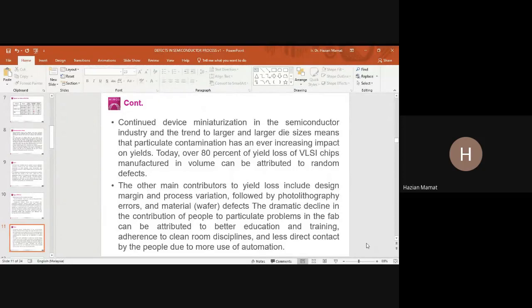Okay. But as we know, if we have a larger wafer size, we can keep the number of malfunctioning chips or defects to the lowest. That's why foundries are getting bigger and bigger wafer sizes. The other main contributors to yield loss include the design margin, process variation, followed by photolithography errors and material (wafer) defects. The dramatic decline in the contribution of people to particulate problems in the fab can be attributed to better education and training, adherence to clean room discipline, and less direct contact by people due to the use of automation.